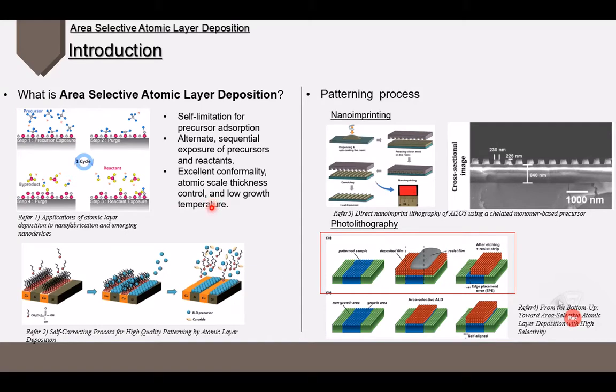In the traditional ALD process condition, films are made on the whole surface of the substrate. Thus, in order to make patterns, an additional patterning process has been necessary. For example, photolithography and etch processes are needed to make patterns, or patterned film can be formed by the nano-imprinting method with solution process. However, due to the very low etch rate of materials such as aluminum oxide, edge placement error, and different properties between ALD films and solution processed film, demand for area selective ALD has arisen in the semiconductor and display industry.